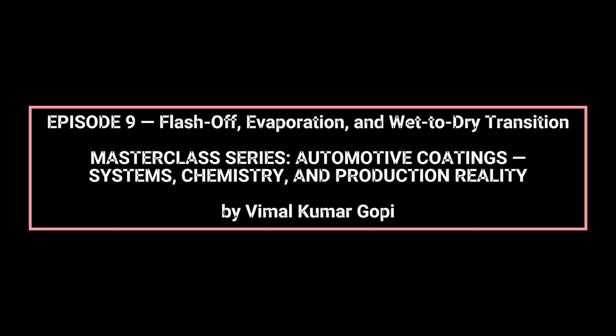In clearcoats, flash-off governs surface leveling and final texture. Early solvent loss increases yield stress, locking in orange peel. Delayed evaporation improves leveling, but raises the risk of solvent popping during bake if diffusion pathways are insufficient. Clearcoats are particularly sensitive because they lack pigment to mask surface defects, making flash-off control critical for appearance metrics such as DOI, haze, and gloss.